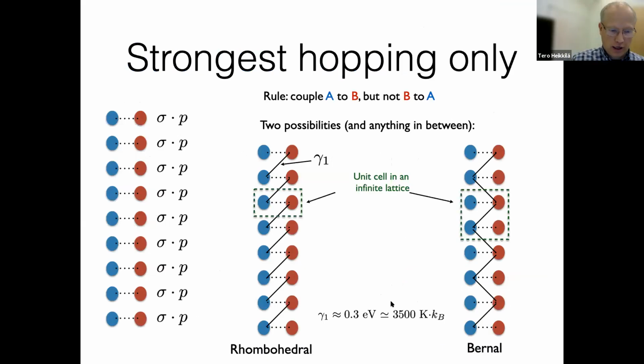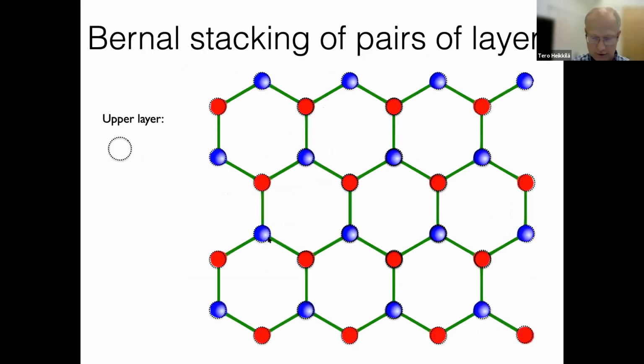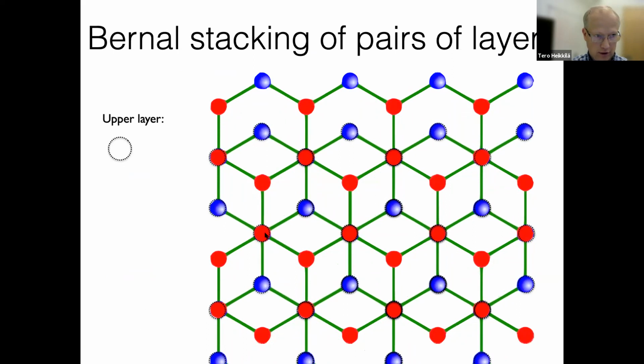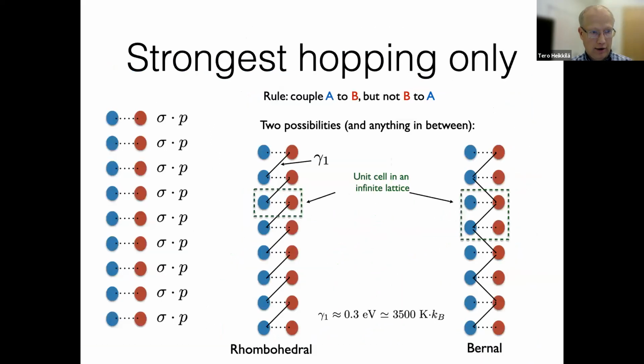But so that you get some idea of what happens to the spectrum if you only consider the strongest coupling between the layers, which is basically this gamma one, which is the one connecting these atoms on top of each other. Yeah, and then one way to picture this system is that we have lots of graphene layers where the red and blue atoms are now the A and B sites of the individual unit cells, and basically they are coupled at finite momentum due to the sigma dot p Hamiltonian of graphene. And now once you start including the interlayer coupling, you couple blue to red, but not red to blue. Okay, and this way you can create either this rhombohedral stacking or Bernal stacking.